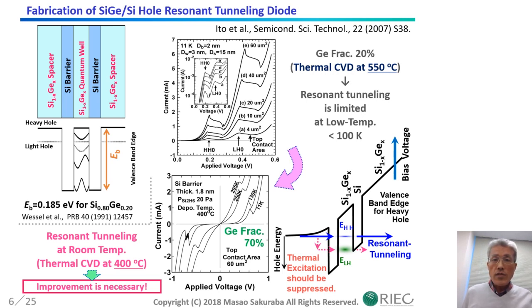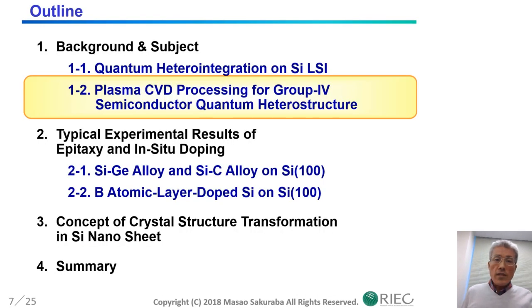I think this is due to the large lattice mismatch, and the intermixing during epitaxy is considered at the growth temperature. Therefore, further increase of germanium fraction seemed to me highly challenging in the conventional process using thermal CVD. In this way, the key technology is energy band modulation using nanometer scale heterostructure and local doping with suppressed intermixing. Therefore, in our group, a low energy plasma CVD process has been investigated for lower temperature epitaxy.